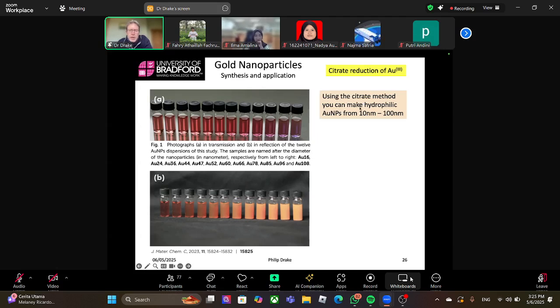So using the citrate method, you can make hydrophilic, water-soluble gold particles from 10 to 100 nanometers. You can very carefully control the size. You can make different sizes, and you can see the different properties. That's in reflectance mode. These kinds of particles are stable for years. We've seen Faraday's particles, they're almost 200 years old and still not settled. The bigger particles start to precipitate and will slowly settle down. After a few weeks, these will show sedimentation, the solution will become clear, and you'll have a film on the bottom. You can remix and reshake them very easily, but they do settle out over time.